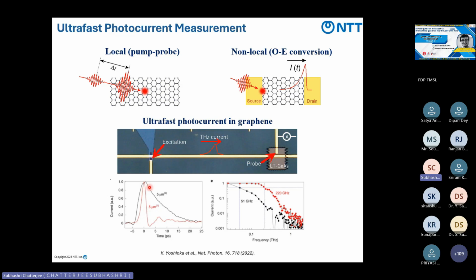This is for graphene, and these two are different areas. 5 micron refers to the size of the active area, but different mobility was used - different graphene mobility. By changing the graphene mobility, we get different decay signals at different times. So now you can distinguish how fast the signal is, and if this is within 1 to 2 picoseconds, you can say this is not coming from normal photovoltaic or bolometric effect.